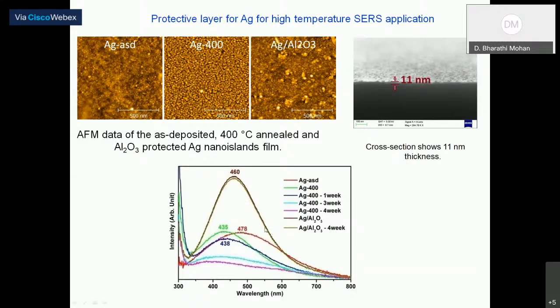Whereas if you look at the film that is coated with Al2O3 and stored for 4 weeks, there is not much change in the SPR maxima as well as in the full width at half maximum of the SPR. So this way, one can protect the silver with the Al2O3 layer to avoid the oxidation.